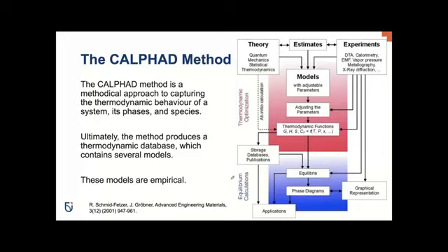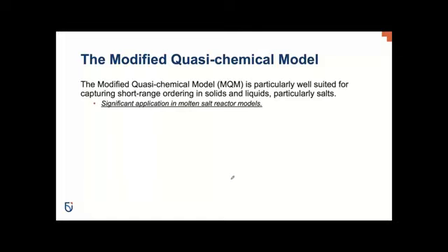And the CALPHAD method itself is effectively a methodical approach to derive these thermodynamic models, primarily from experimental data. So that is to say that these thermodynamic models are empirical by nature. You derive these models using experimental data as input. One of those models that is particularly well suited for molten salts, which is again the topic of the SAMOSAFER group, is called the modified quasi-chemical model.